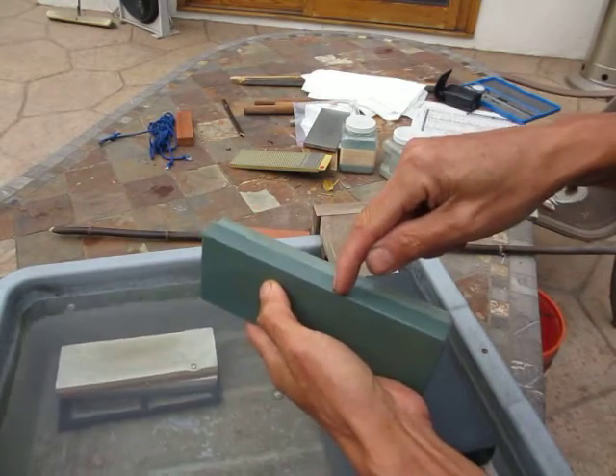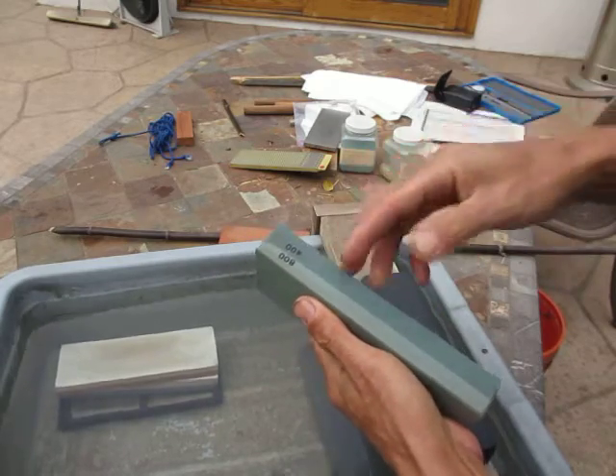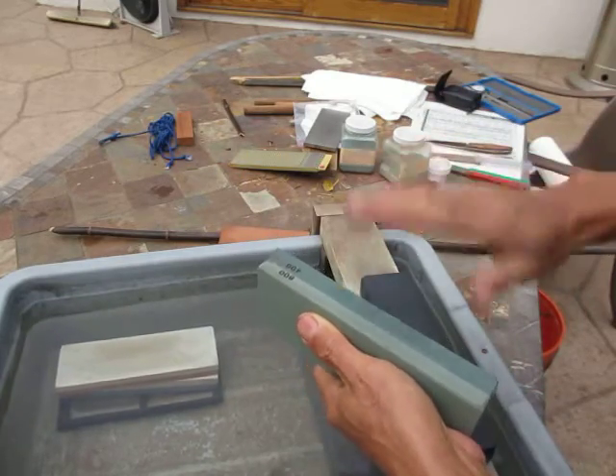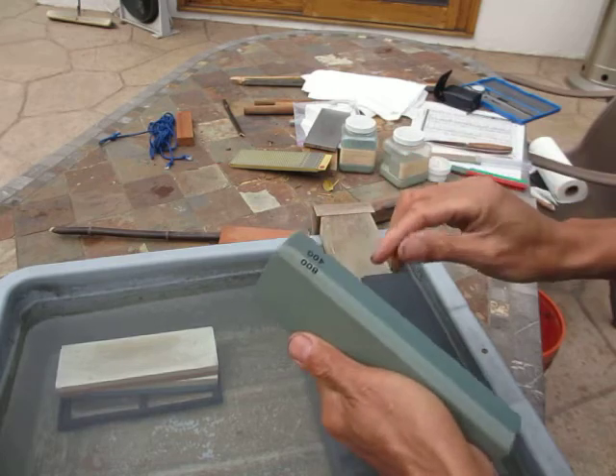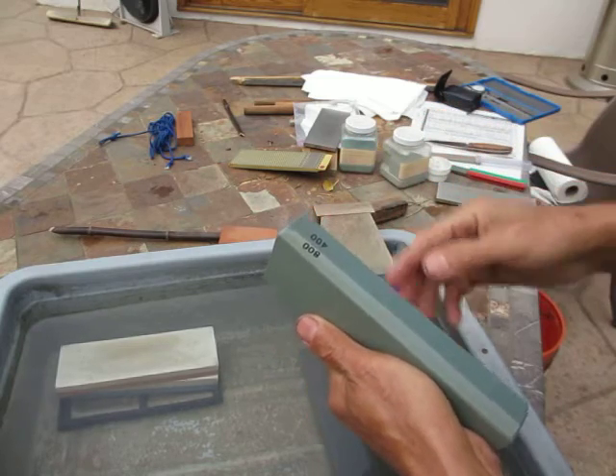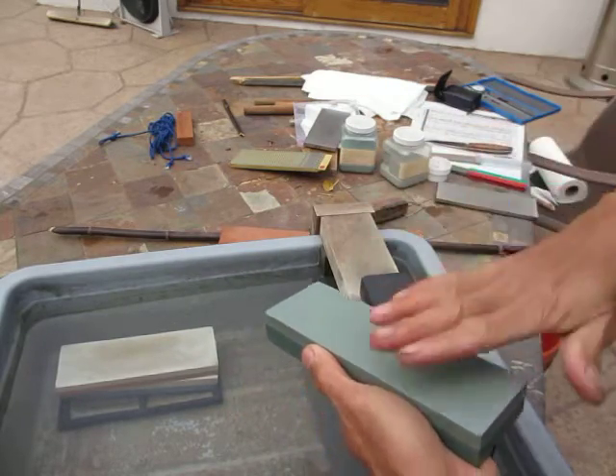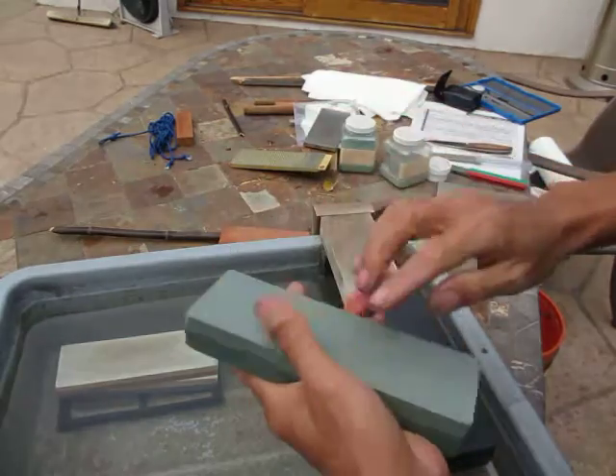When you go beyond that to something here — the green silicon carbide at 400 and 800 grit — at 400 you still do some plowing. But actually it will try to knock the carbide out of everything; it will clean the jaggedness of everything else. But at the same time, it's not really effectively saving the carbide itself. The carbide is about two to five microns — you're not saving it. You either weaken it by colliding into it, or you knock it out. By 800, this thing is fairly soft, leading — you will feel your knife dull. But I do that sometimes to clean the etched shoulder, the bevel shoulder, to smooth it, so it's more like a convex, so they can transition — so less wedging.